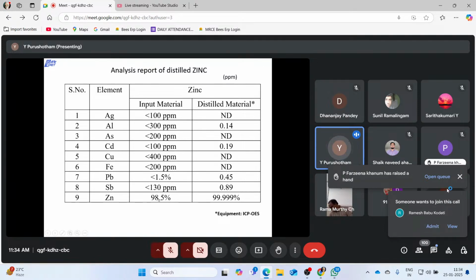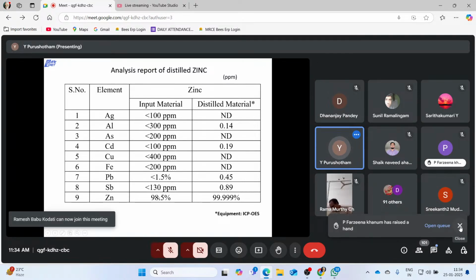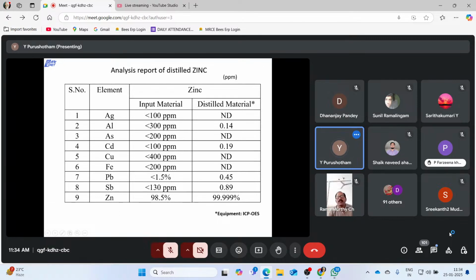After vacuum distillation, when we analyzed using ICP-OES equipment, you can see the 1.5% lead has been reduced to 0.45 ppm. Such an effective technique, this vacuum distillation, and other impurities went to the non-detectable range. Finally you are getting 99.999 percent purity.